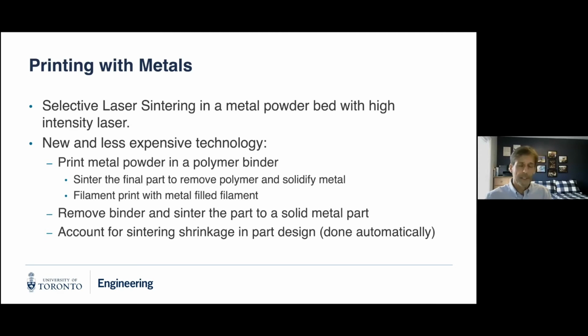And sintering is just heating it up, but not melting it. So it keeps its shape, it shrinks, and we have to account for that sintering shrinkage. But of course, that's all done automatically in software. And it is possible then to pretty rapidly build a metal part this way. It takes a little while to sinter it, but at the end you have a metal part, which, because the metal doesn't have this problem with diffusion, is a pretty strong, highly dense metal part.